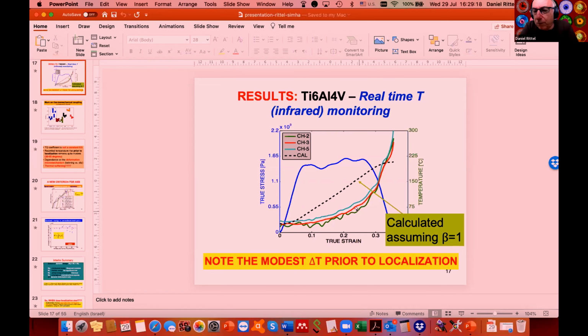And that excludes, of course, one thing, which is called the hot spots. That's another problem for discussion. Hot spots means simply that you may have very small and very hot spots inside the material, very localized heating, which we've never seen, but you could suspect it. People who deal with explosives are very familiar with hot spots because this is what ignites an explosive. So if there are such hot spots, they should be considered. We didn't see them, but that's due to the spatial resolution of our detectors, which is of the order of 30 by 30 micron.